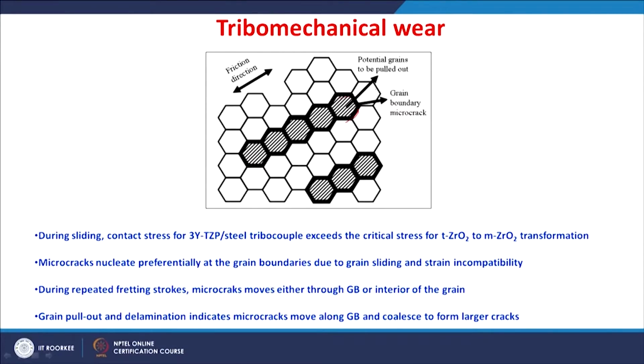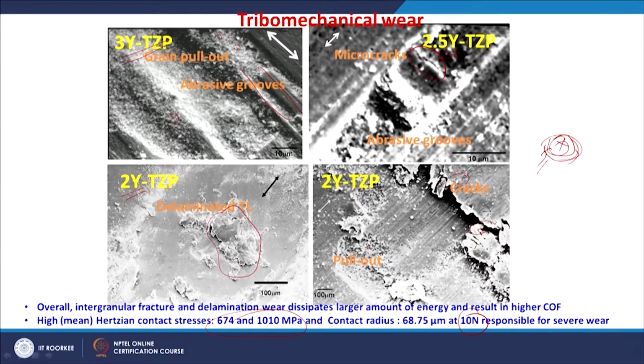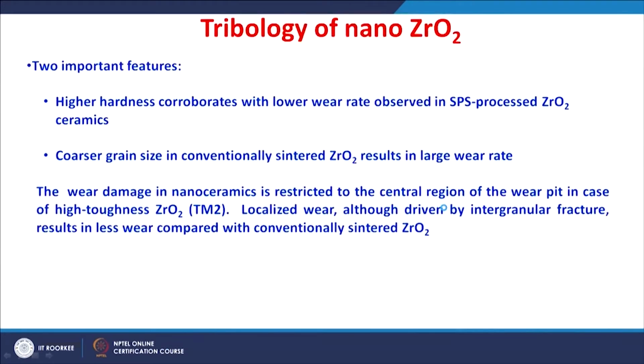So, the grain pullout and delamination both indicate the microcracks move along the grain boundary, coalesce with each other and then form longer cracks. So, you can see the cracks also where there is a surface layer, there is a delamination of this layer. So, let us understand the tribology of this nanoceramic zirconia ceramics.